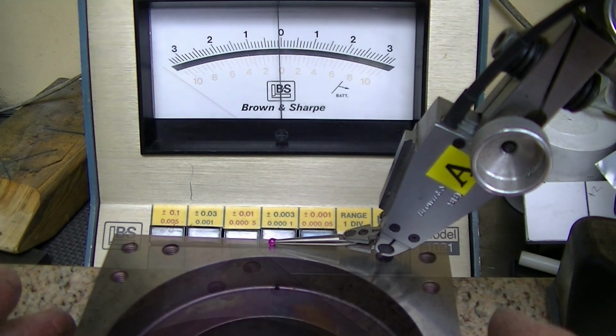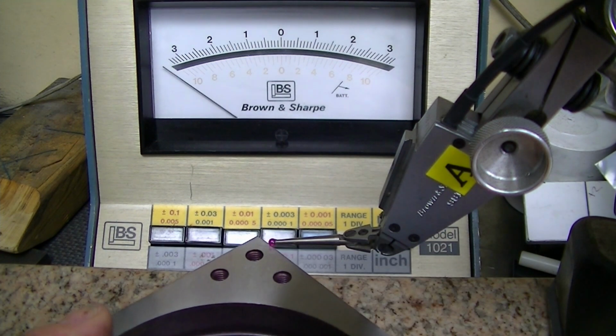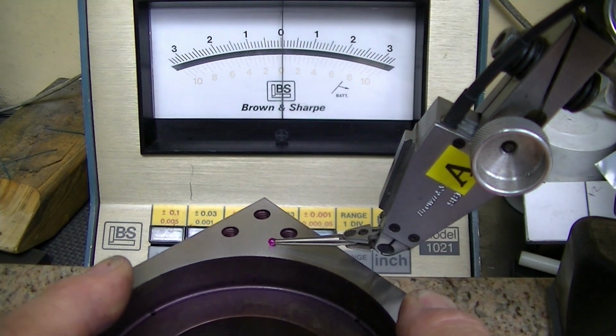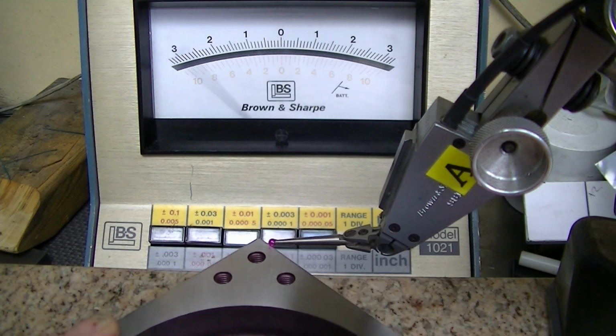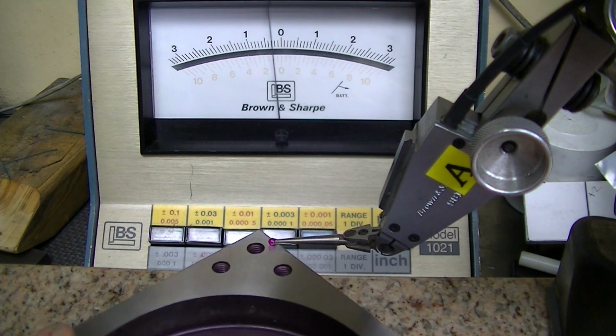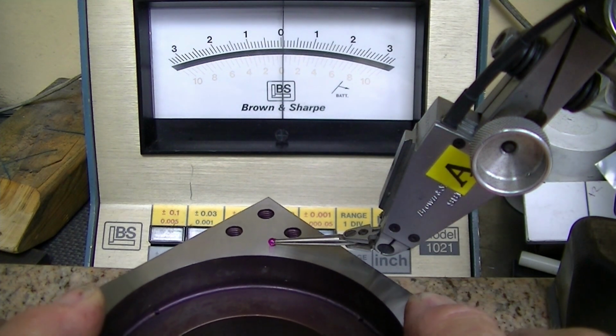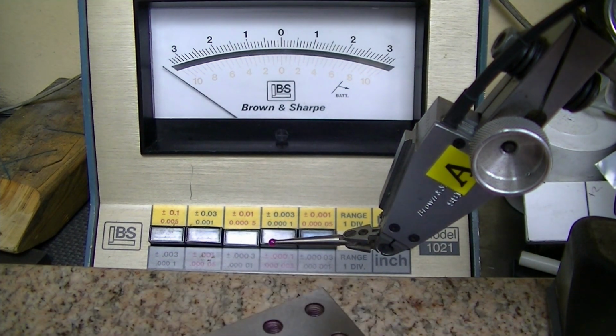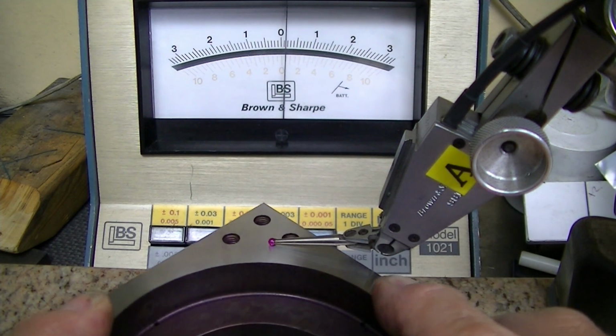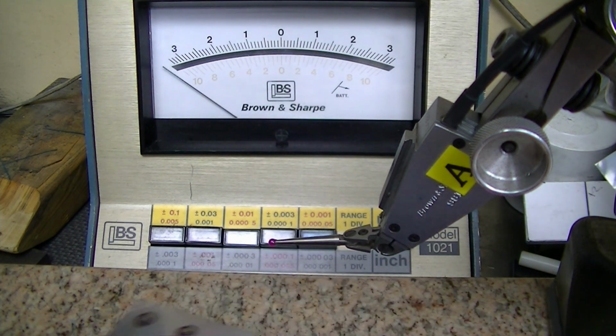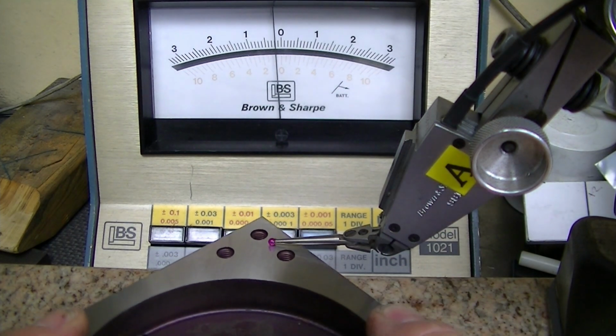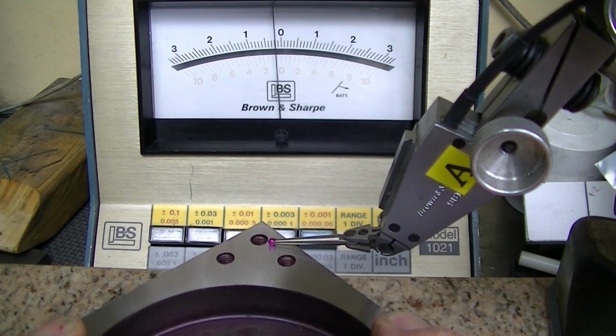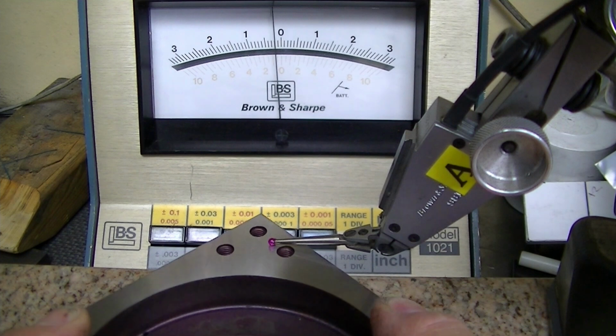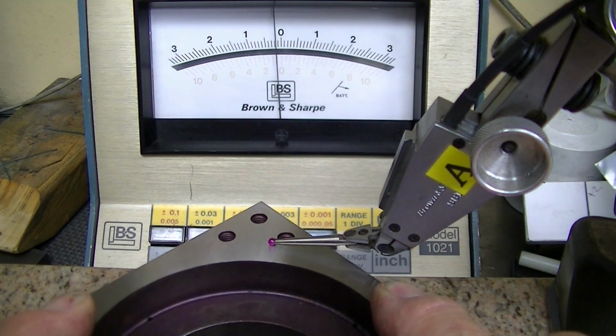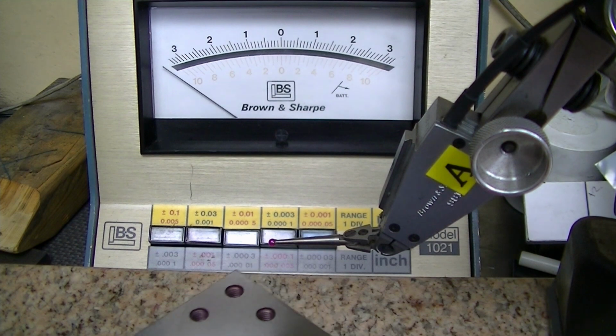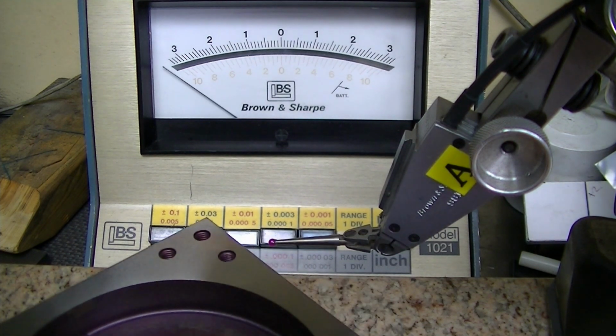Pretty good. 0. Now I'm running over the 4 corners, looking for the amount of change from inside to outside. Very little there. Probably 10 millionths. Maybe 20 on this one. Nice, 10 millionths there. And that's low in general. That's low, probably 20-25 millionths from the other zeros, but still well flat enough for what we're doing.